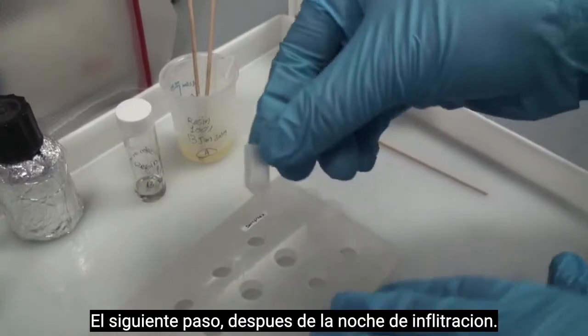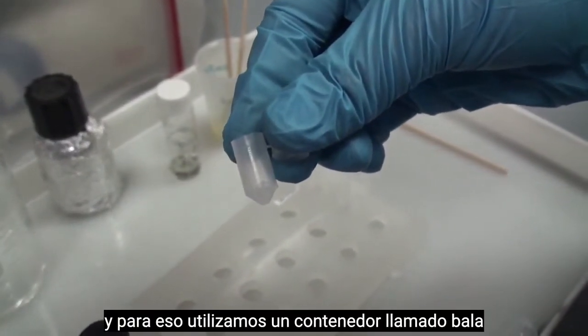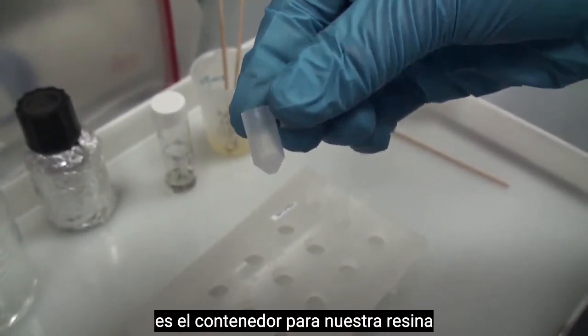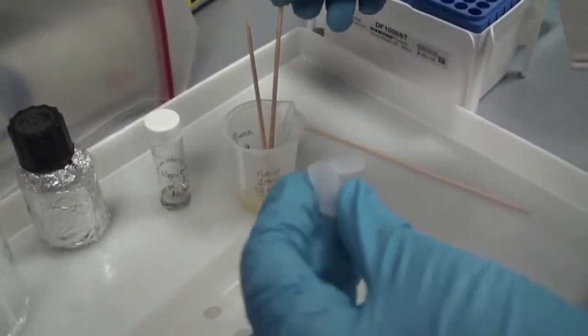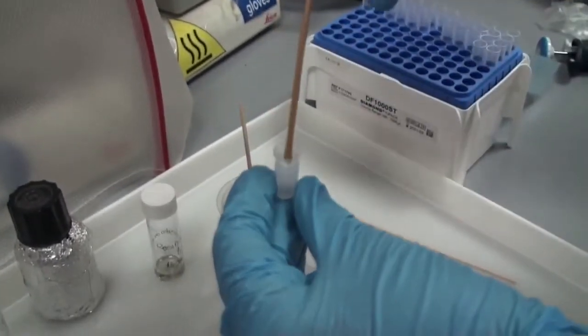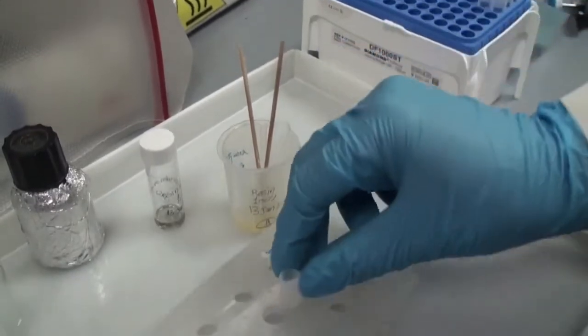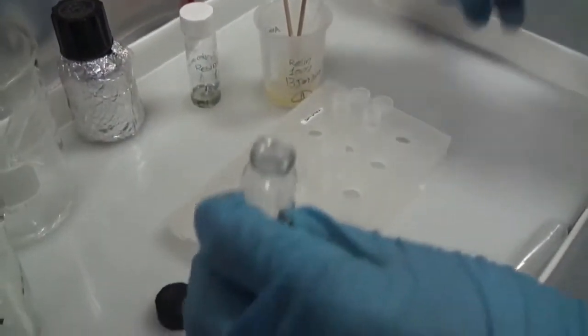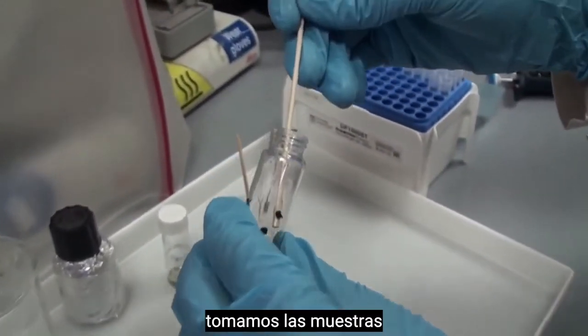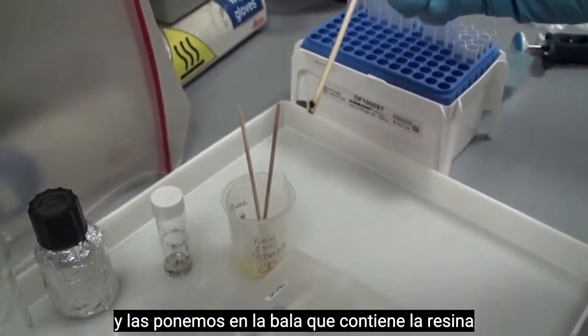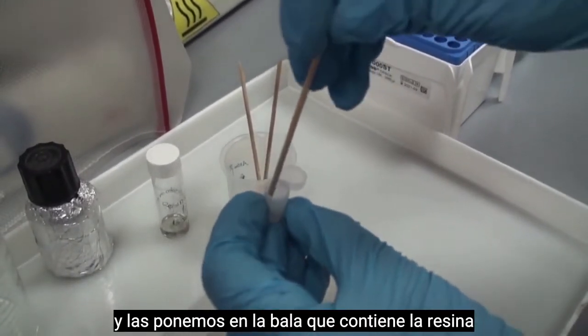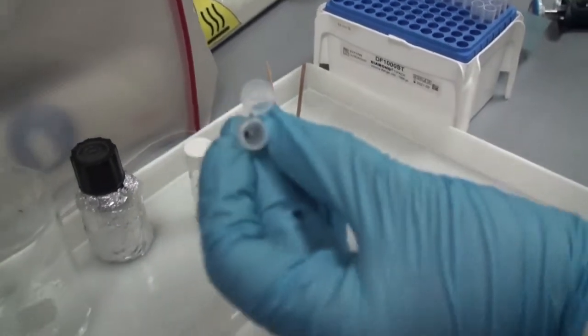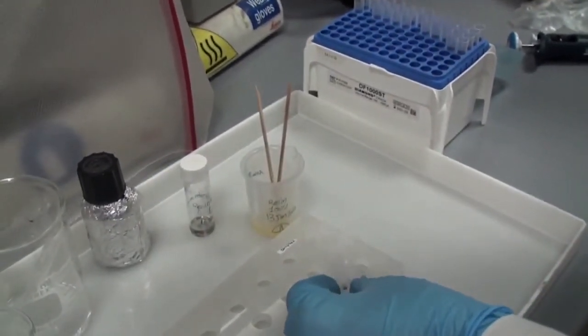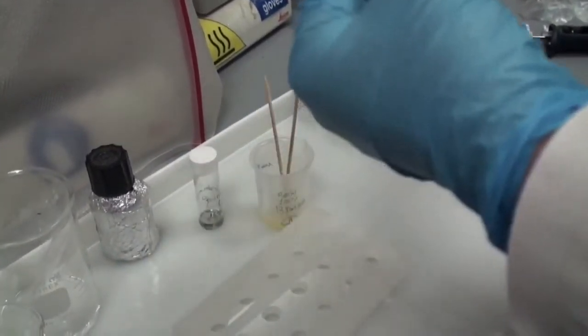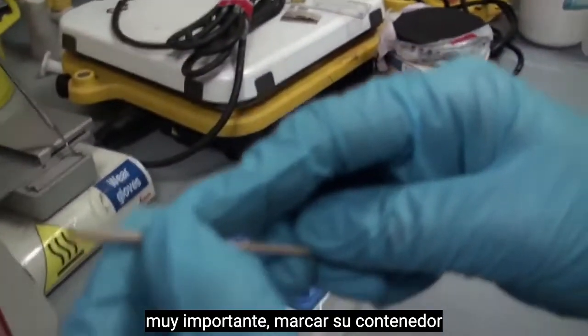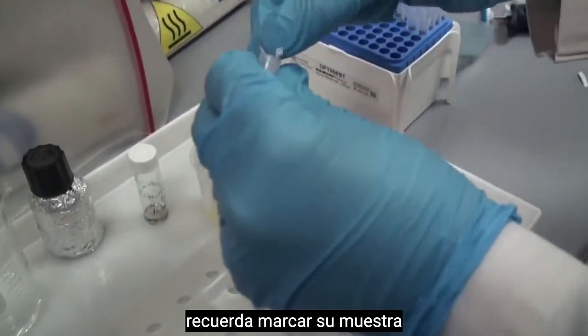The next step after the overnight infiltration is to do the embedding. So for that we use what we call a bullet. This is the bullet. It's a container for our resin. So it's kind of a mold, and we put the resin inside it. We take our sample and place it within the bullet that has the resin in it. Very important to remember to label your specimen, your sample, so you won't lose it.